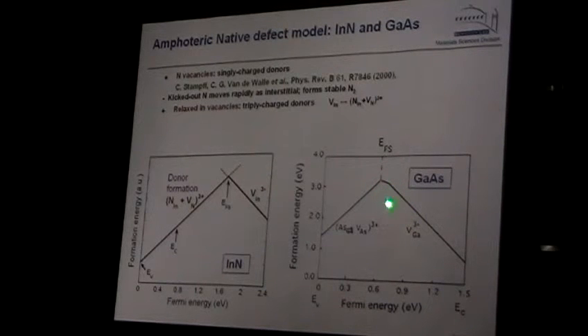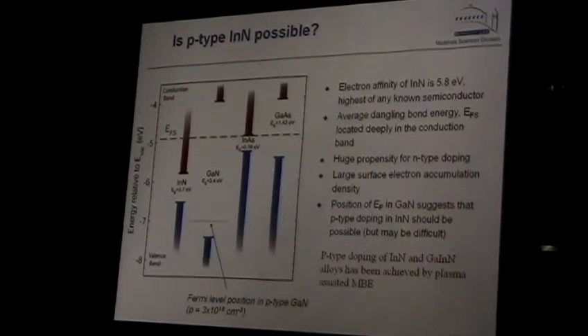This is very well studied in gallium arsenide, and it is known that this is how it behaves. So of course in indium nitride, the stabilization energy is in the conduction band, so we have very high conductivity in fact. Whereas in gallium arsenide, the stabilization energy is in the middle of the gap, and then it is a high resistivity material. So there's a big difference.